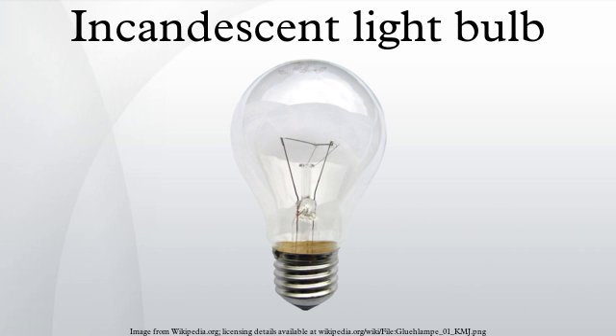By 1910, a process was developed by William D. Coolidge at General Electric for production of a ductile form of tungsten. The process required pressing tungsten powder into bars, then several steps of sintering, swagging, and then wire drawing. It was found that very pure tungsten formed filaments that sagged in use, and that a very small doping treatment with potassium, silicon, and aluminium oxides at the level of a few hundred parts per million greatly improved the life and durability of the tungsten filaments.